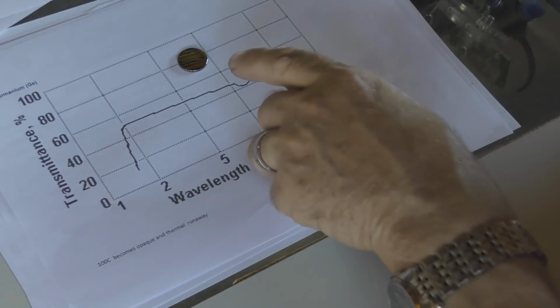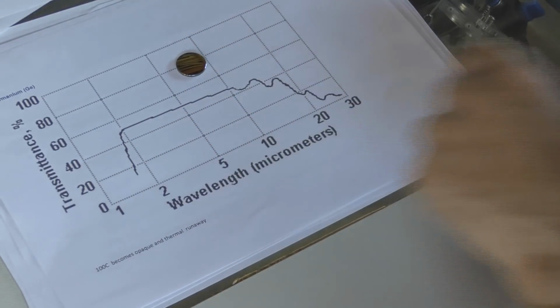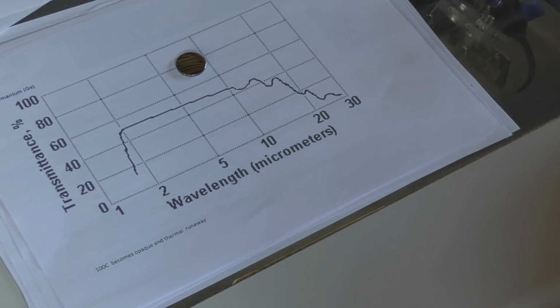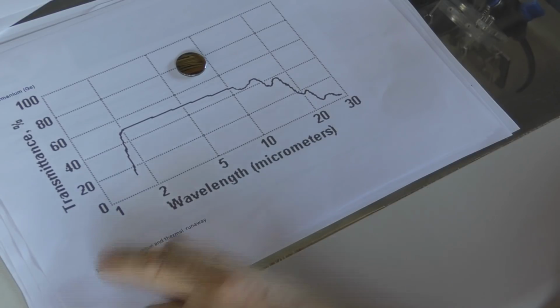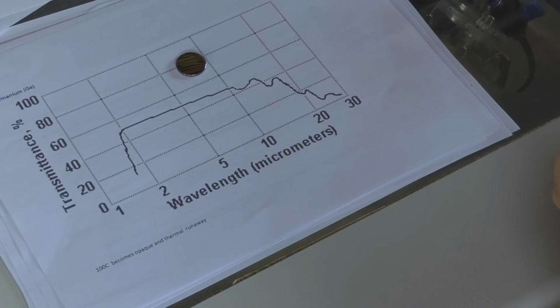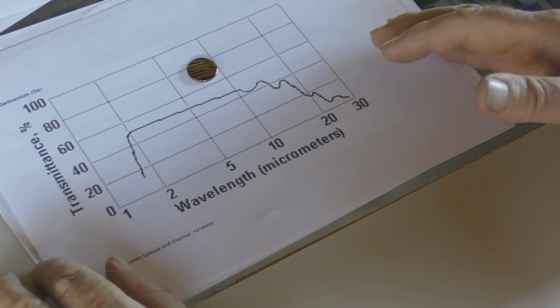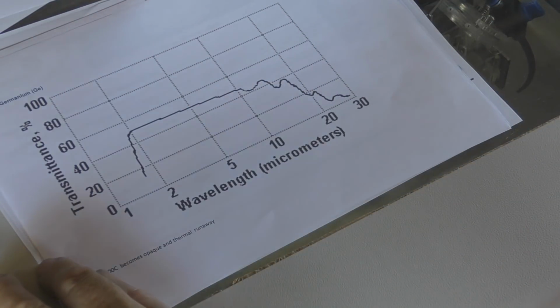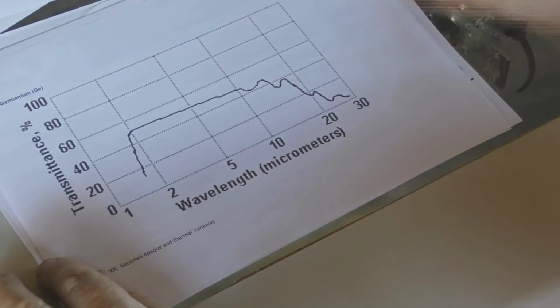If you start using this in a laser machine which is much over 40 watts, if you break down this coating that's on here and the infrared light starts getting through to the material underneath, then it will start heating the material up. And although it's transparent at room temperature, once it gets up to about 100 degrees C, this material all of a sudden becomes cloudy and opaque to infrared light. And as soon as it becomes opaque to infrared light, it means it starts absorbing it. And you get thermal runaway and you will pop the lens. It's fairly safe to use if you've got a K40 machine, but don't even consider a germanium lens for any other type of machine. 60 watts and above, stay with gallium arsenide or zinc selenide.